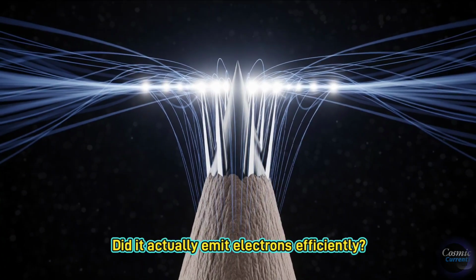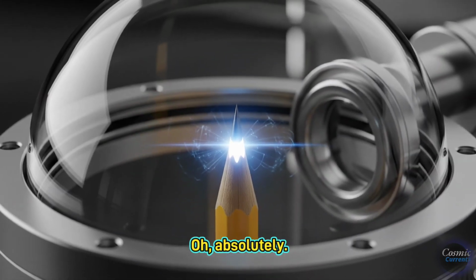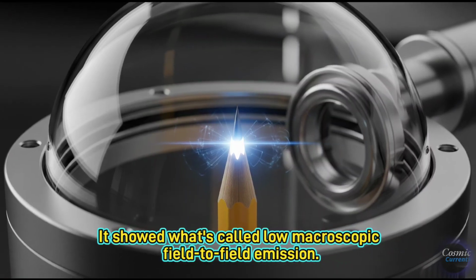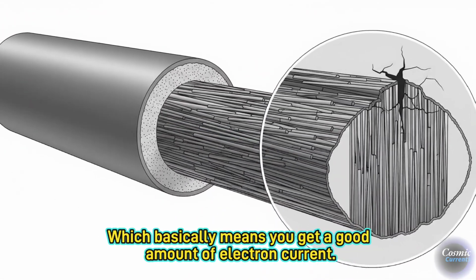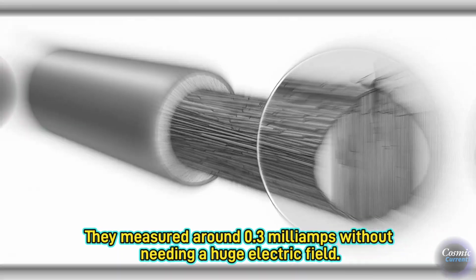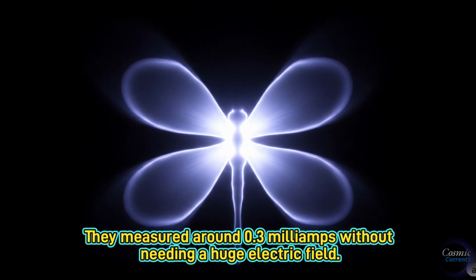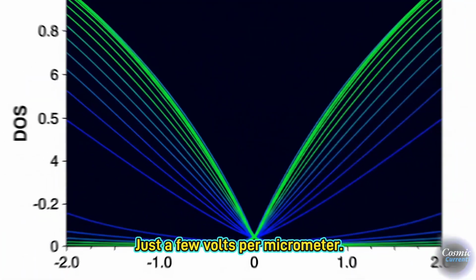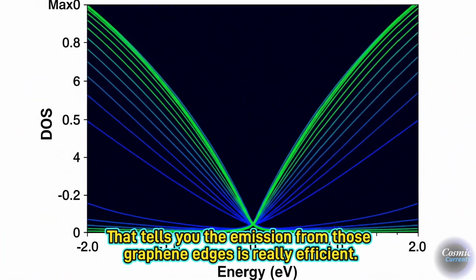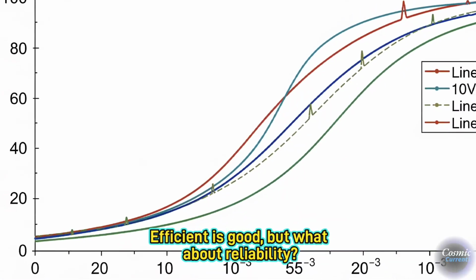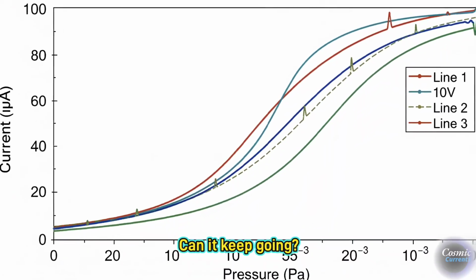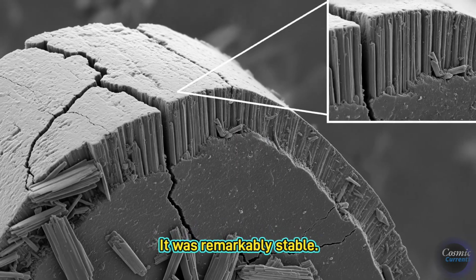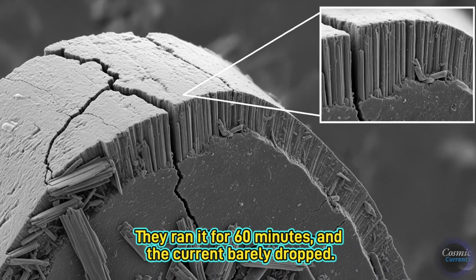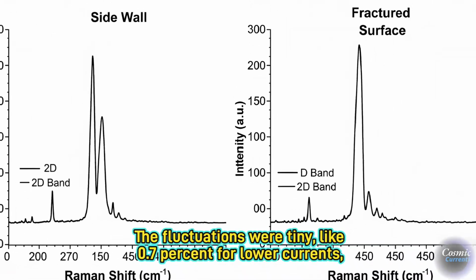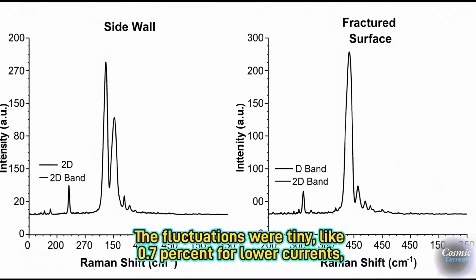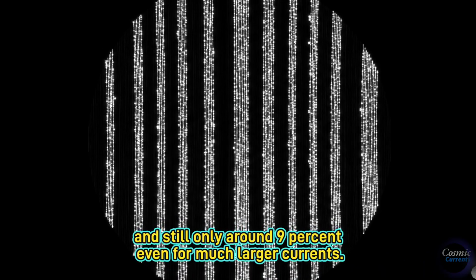What about performance? Did it actually emit electrons efficiently? Oh, absolutely. It showed what's called low macroscopic field emission. Which basically means you get a good amount of electron current. They measured around 0.3 milliamps without needing a huge electric field. Just a few volts per micrometer. That tells you the emission from those graphene edges is really efficient. Efficient is good, but what about reliability? Can it keep going? How does it hold up? That's another strong point. It was remarkably stable. They ran it for 60 minutes, and the current barely dropped. The fluctuations were tiny, like 0.7% for lower currents, and still only around 9% even for much larger currents.